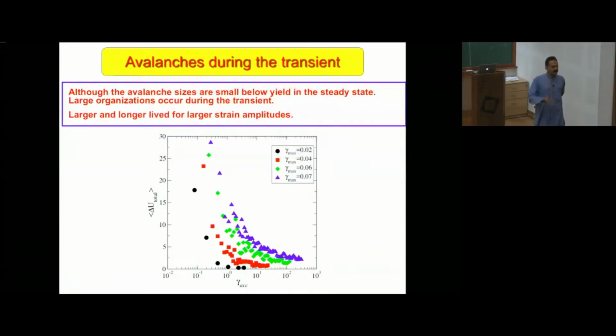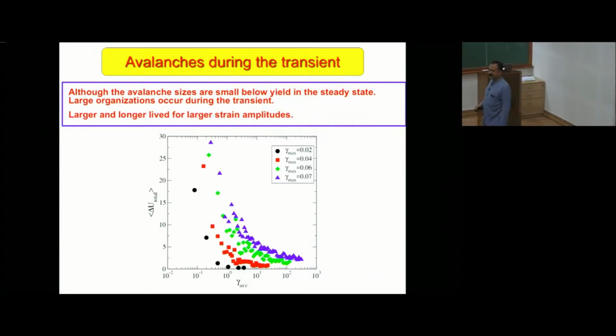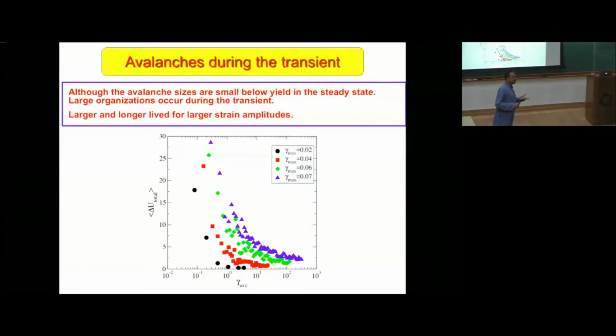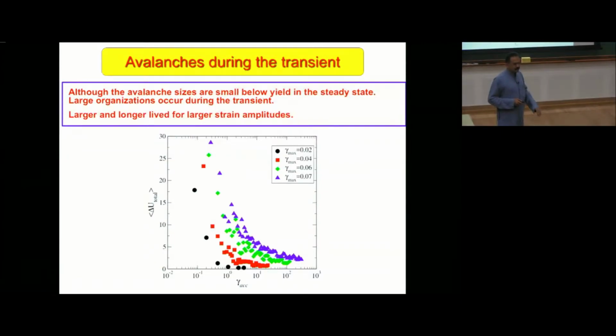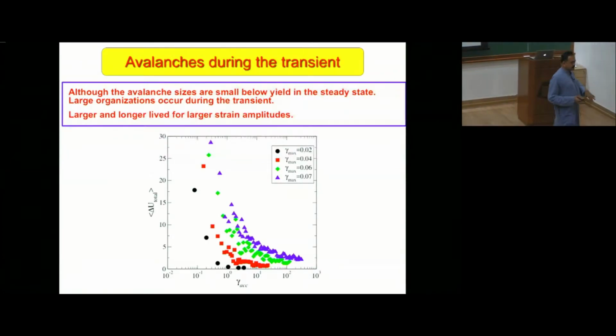But there are things that happen in the cycles in which you train the system. These basically anneal out various reorganizations that can take place, which people would see, for example, if they simply did uniform shear. And this is now the size of the energy drops plotted against accumulated strain, the number of cycles, roughly speaking. And what you see is that these sizes get bigger and bigger as you increase the amplitude of deformation, and they last longer and longer. So there's a lot of restructuring that takes place in the process of training the system.